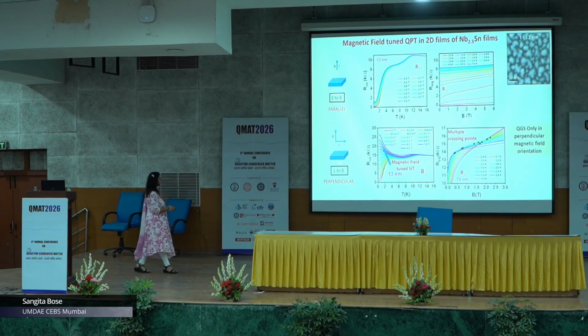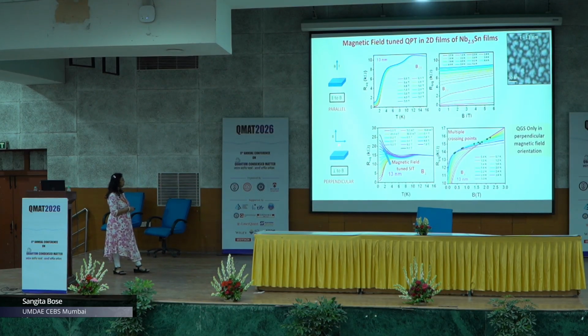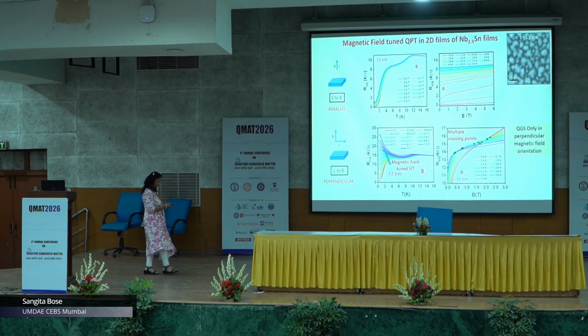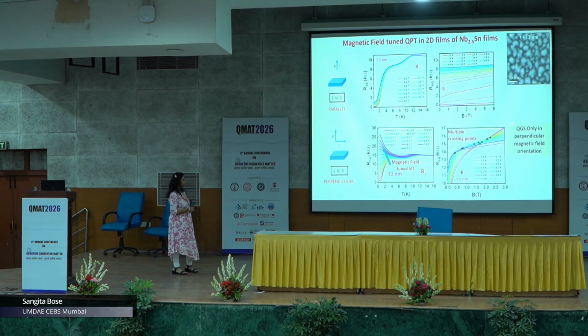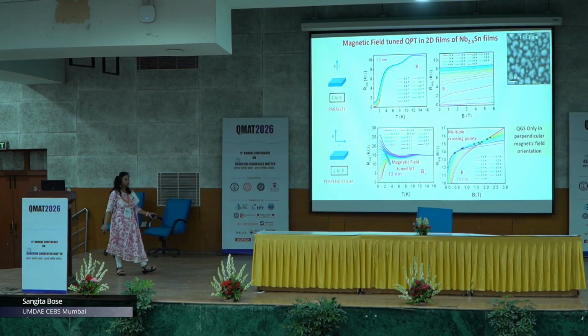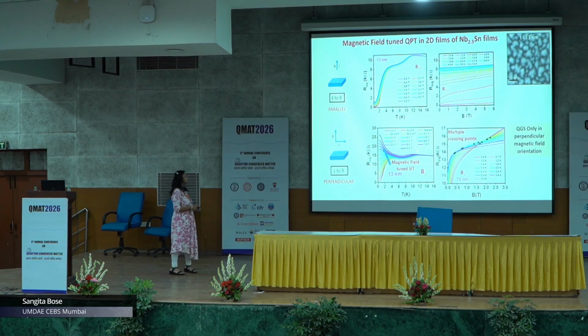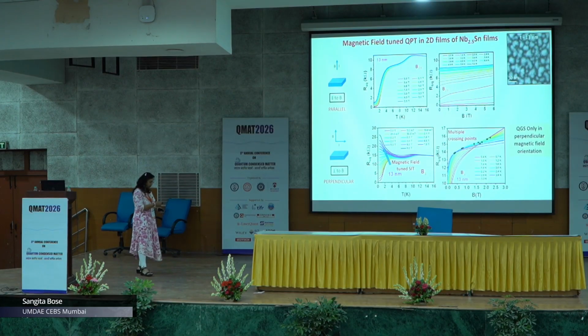Now we go to the perpendicular orientation. The same film we measure in the perpendicular orientation. We tune the magnetic field, and what we notice is that for these films you start seeing this magnetic field tuned superconductor to insulator transition. These are the different magnetic fields we are doing. Looking at the magnetoresistance isotherms, this is exactly what I had showed you before, with multiple crossing points happening for different temperatures. So we can say that this 13 nanometer film is showing some of the characteristics similar to the quantum Griffiths phase which we explained just before.